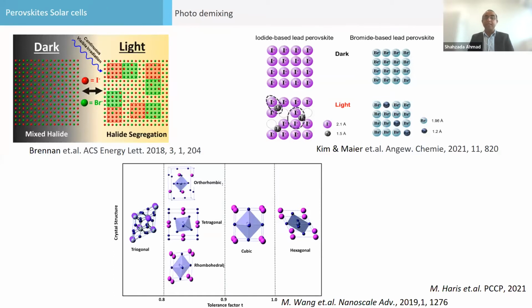Coming back to what I said, the mixed perovskite was very good, but what we found is that in the light there is halide segregation. In the dark phase they are very good, mixing is there, but in the light they have halide segregation. The iodine is in one place, the bromide is in another place. By doing so, they form high band gap domains and low band gap domains. If you look with AFM and Kelvin probe force microscopy, you will see they form high band gap and low band gap domains.